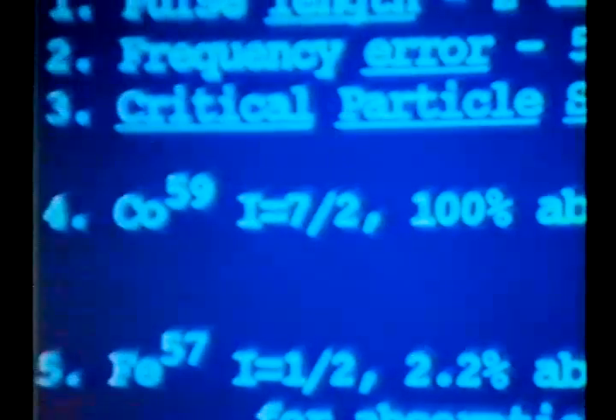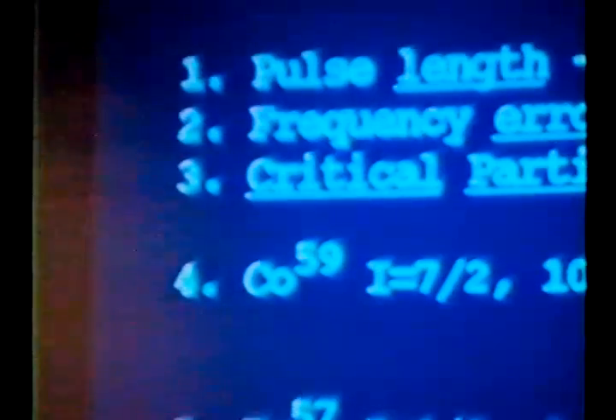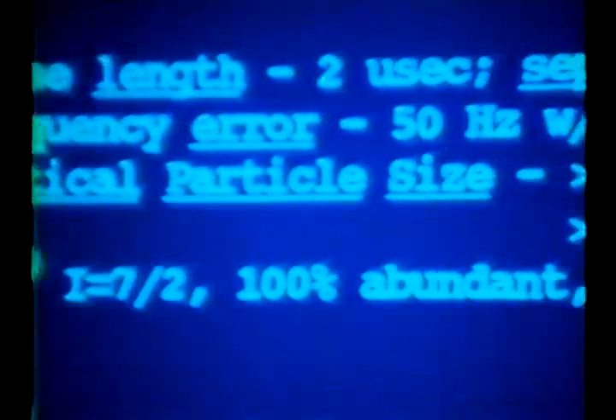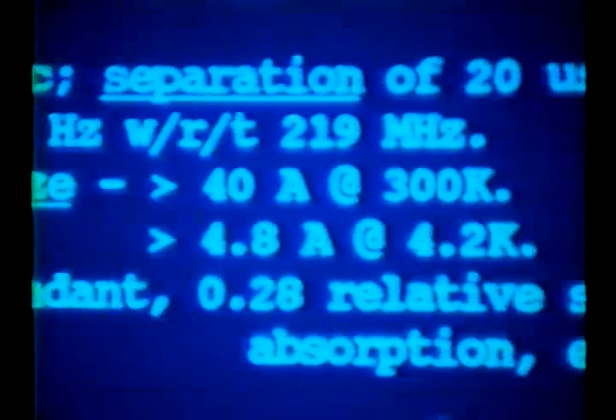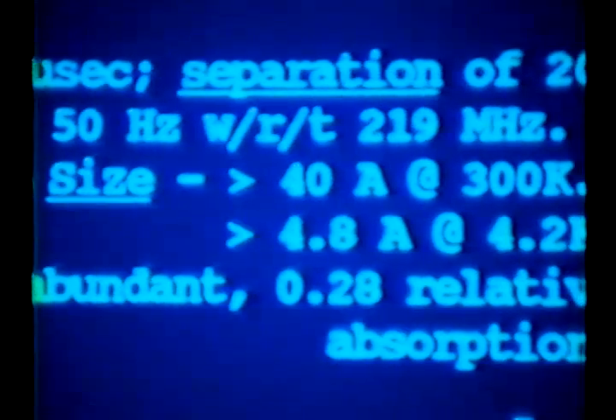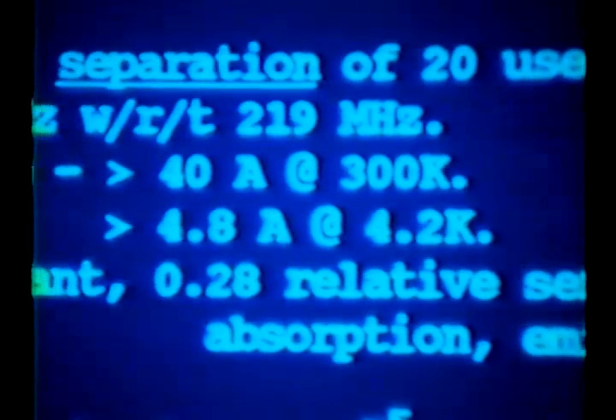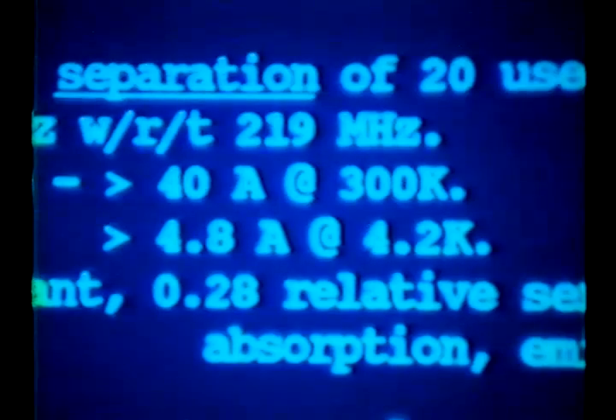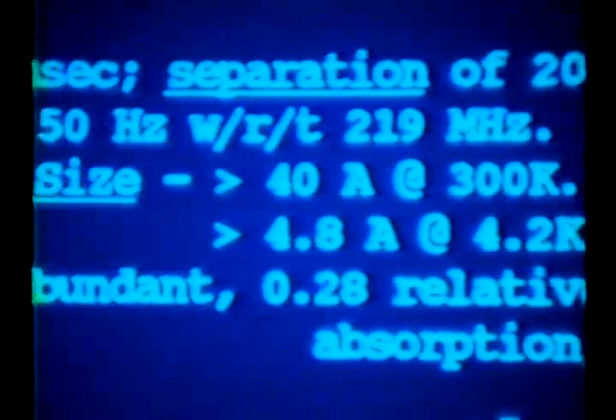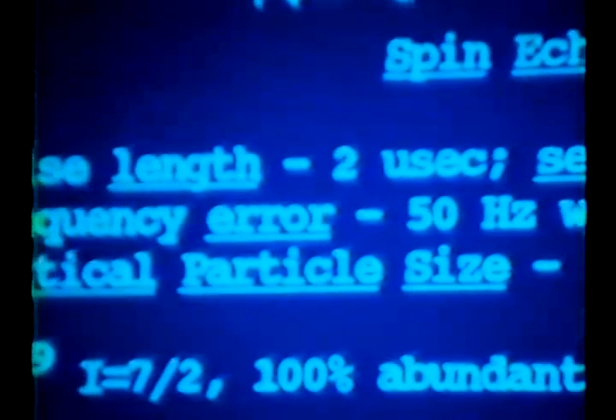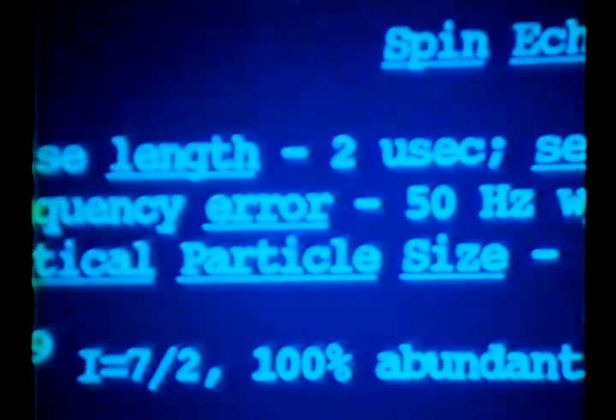Again, it's primarily been used in the physics literature, and Uday Rao collaborated with Murty at Grambling to do the first experiment, continuous wave. Spin echo is a little bit more sensitive. You can perhaps get a little more information with the spin echo technique. What do you do? You apply a pulse. This pulse is about 2 microsecond pulse length with a separation of 20 microseconds.